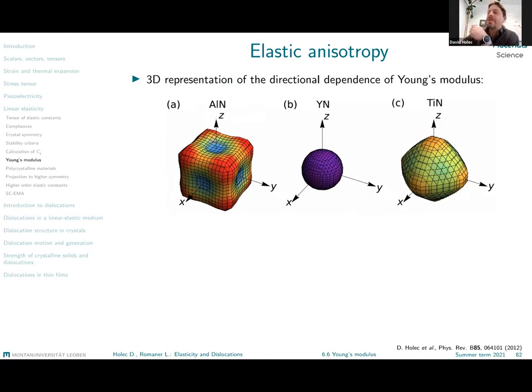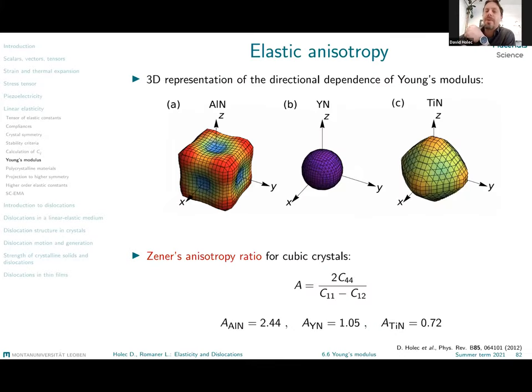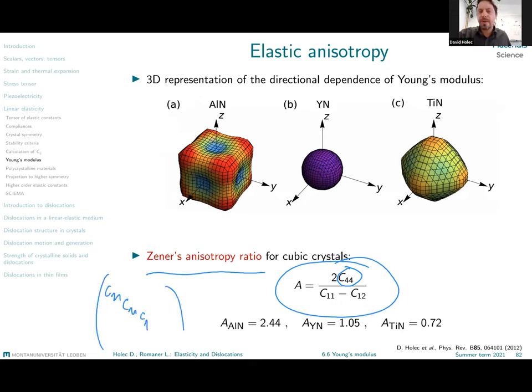This elastic anisotropy is conveniently described and quantified by something called Zener's anisotropy ratio. For cubic materials, it takes this form. And if you think about it, this is exactly the deviation of the C44 component from what would be the value for isotropic materials. If you remember what we showed here last week about the shape of the 6x6 matrix of elastic constants, in which for isotropic materials we said we have C11, C11, C11, C12, C12, C12, zeros everywhere here, right? And then on this lower part of the main diagonal, the values would have been 1/2 (C11 minus C12) for isotropic materials. Well, this is exactly the value that we now calculate here.